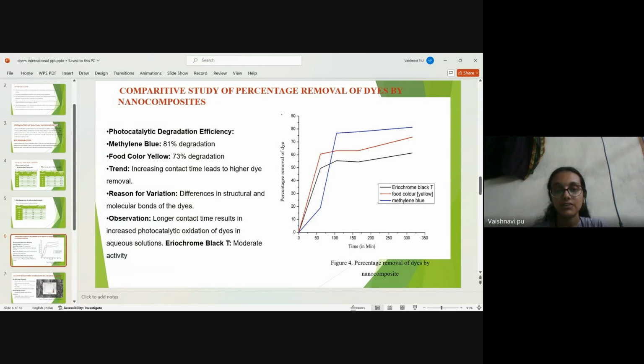In this graph, the blue color shows the methylene blue, red color shows the food color yellow, and the green color shows the Eriochrome Black T. So for methylene blue, 81% degradation can be seen. In food color yellow, 73% degradation can be seen. And Eriochrome Black T has shown moderate activity. The trend is that increasing contact time leads to higher dye removal.